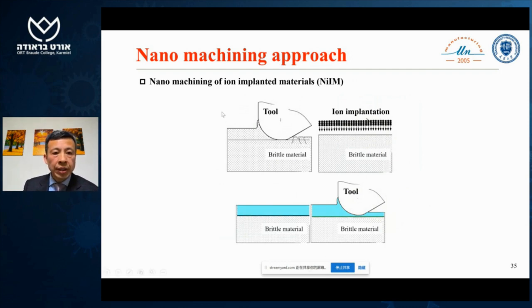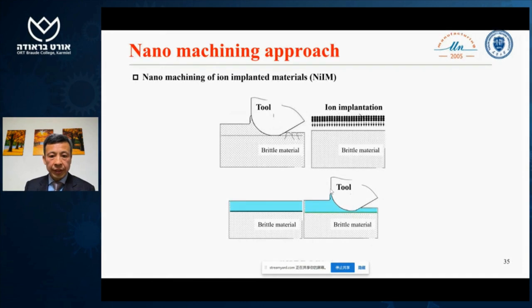We further develop a process by using implantation. The reason we use implantation is because for brittle material, if we cut this kind of material, there is a crack or fracture on the surface. To eliminate fractures and cracks, we use this kind of idea to generate ions into the layer to be removed. Then the property of this layer becomes different. The machinability becomes better. Then we can remove it without cracks and fracture on the surface.